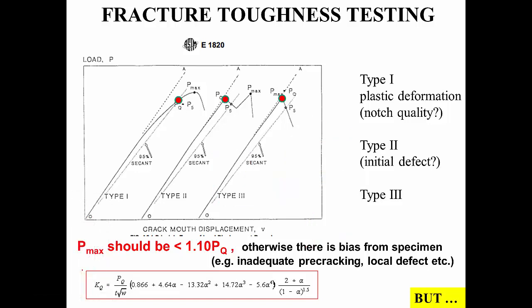So let me delete this. What we have in this graph is load versus crack mouth displacement. And we see three different potential curves. There is always an initial elastic part, so there is a straight line in all three cases. The problem is how exactly should we extract from these curves the maximum load? And of course the problem is not at the initial linear part, but when a peak is reached. And the peak can be reached in three different situations.